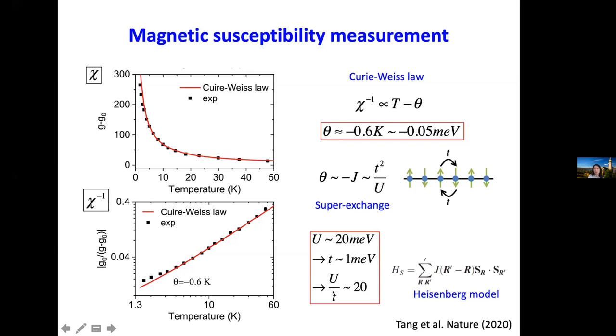And this also gives us a ratio of U over t on the order of 20, and that's in the strongly correlated limit. So it's consistent with the Mott state interpretation.